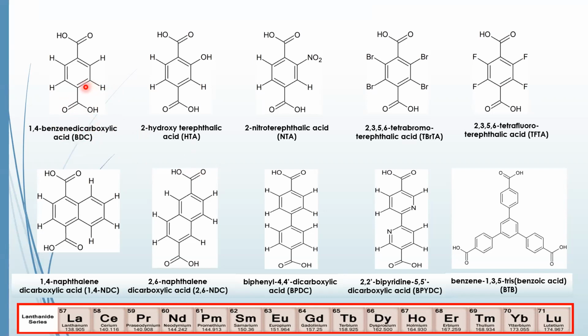And if you notice also, the ligands are related. So in one case here, we have benzene dicarboxylic acid, then we change one functionality to the hydroxy, and we put on the nitro group. And then in these two, we were looking at the tetrahalo, because these offer the possibility for halogen to halogen interactions. And here we are systematically varying the properties of the ligands. Okay, so those are some of the reasons why we chose those ligands.